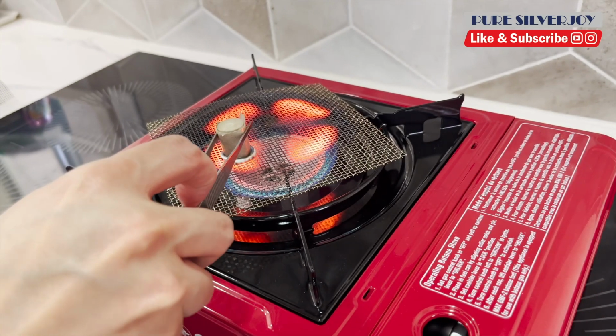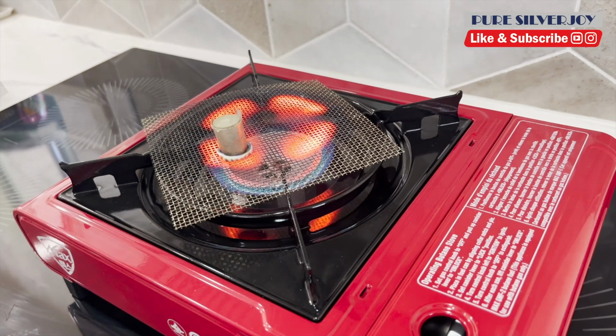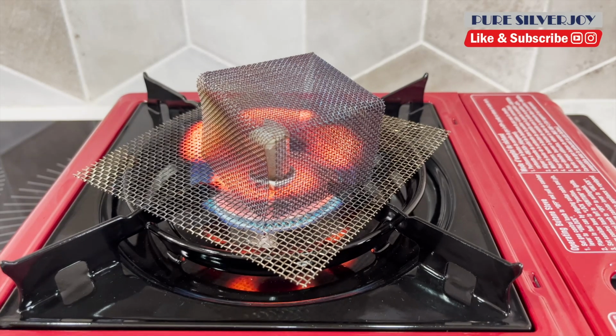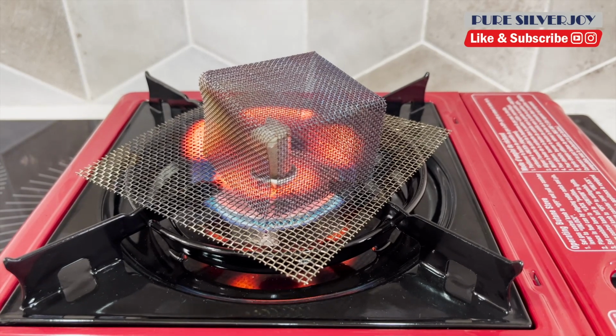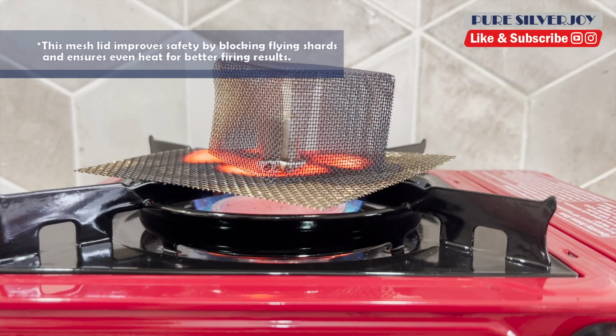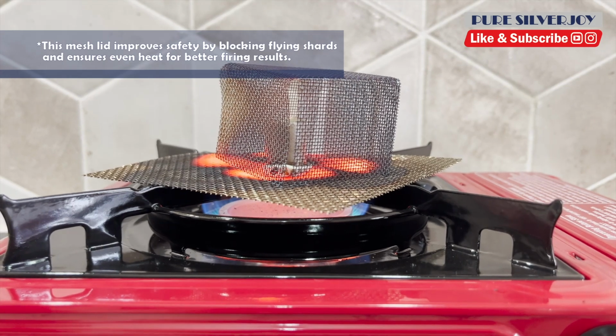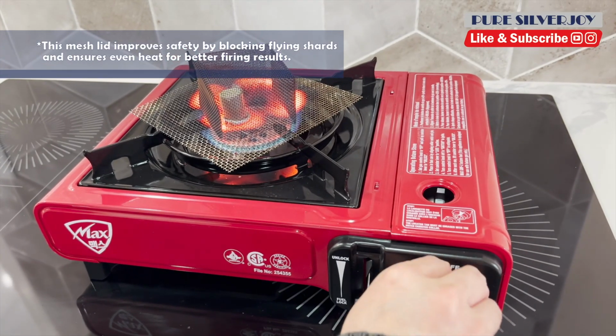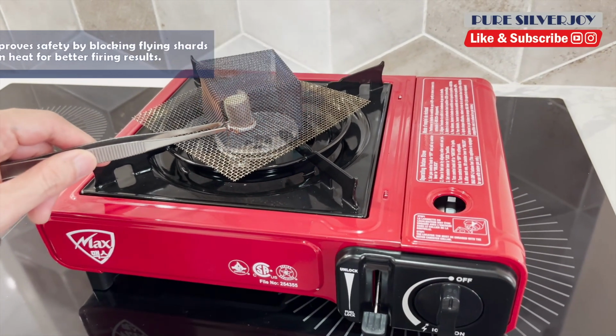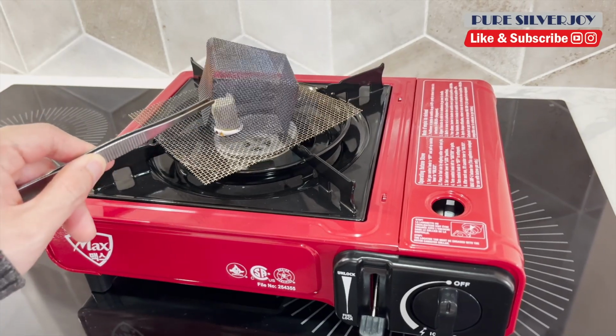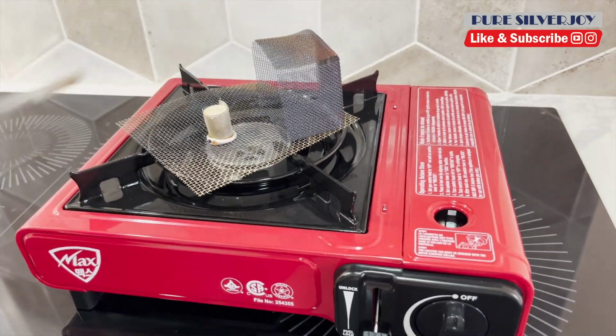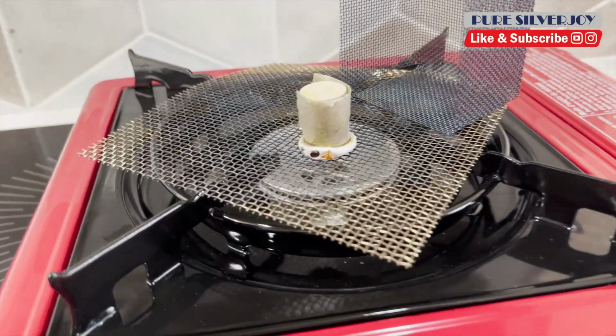If the ring is fully dry, there should be no smoke. If you see white smoke, quickly use tweezers to move the ring away from the flame, and let it gently warm at the edge before continuing. After firing, your piece will become 99.9% pure silver. Let it cool naturally, as quenching gemstone rings in water can damage the stones.